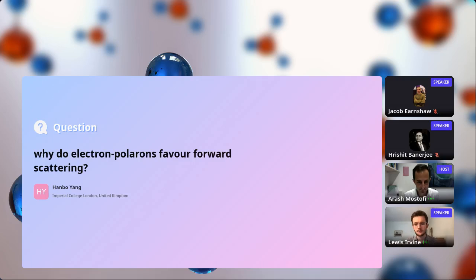Okay, so in general, different mechanisms can prefer forward scattering. In the case of LO phonon scattering, it's because of the Q dependence of the Froelich Hamiltonian. With the Froelich Hamiltonian, you get much stronger scattering with phonons with a small wavevector. And then you're limited by the geometry, and that means that you get this strong forward scattering.